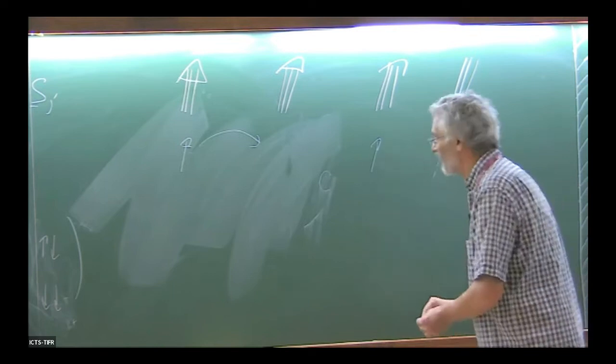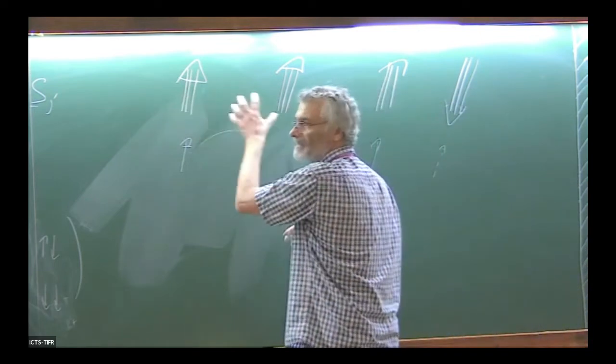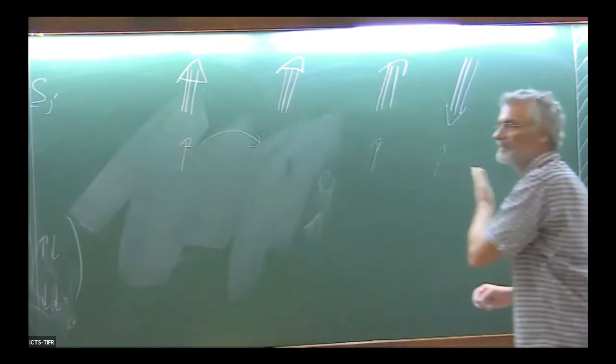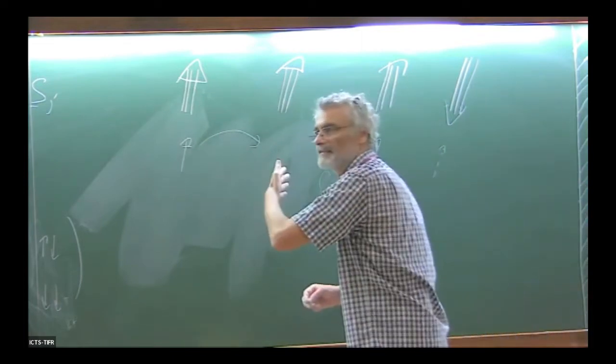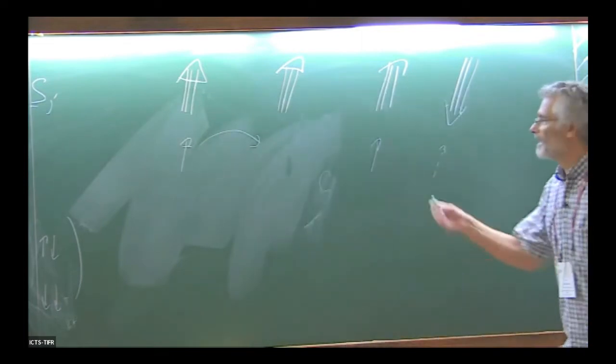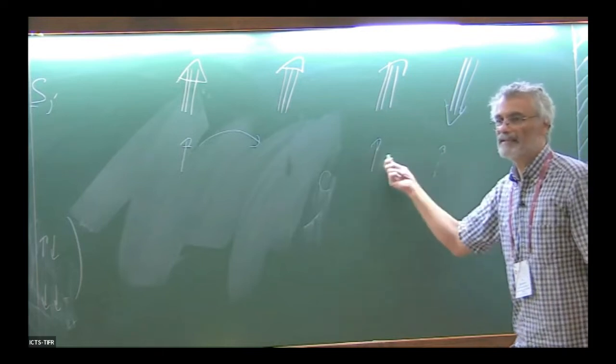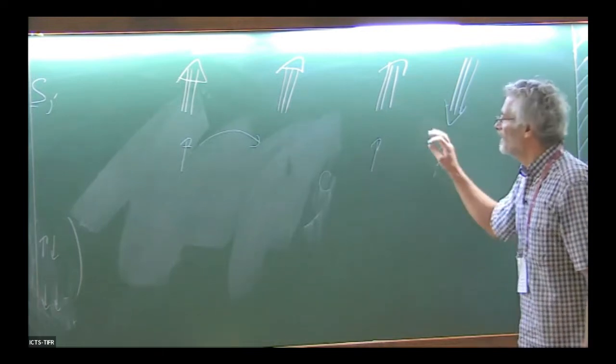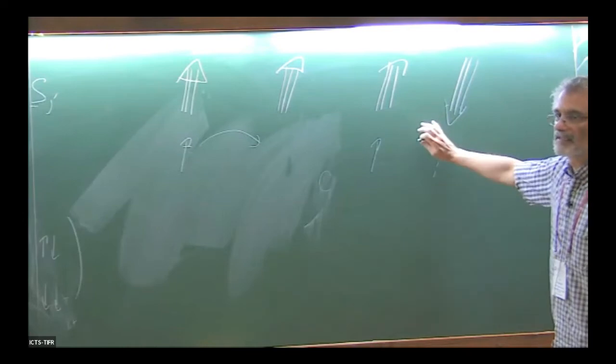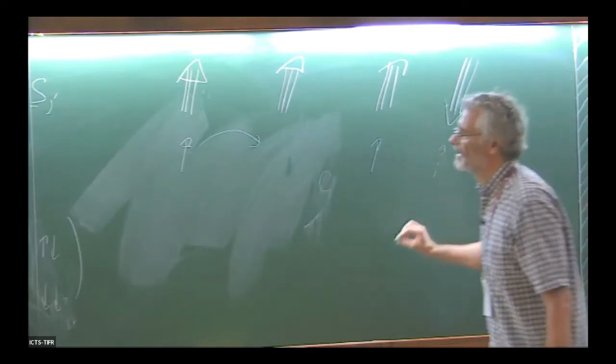So it means that if all the spins are parallel, then the electrons can freely move in the system. If it is an antiferromagnet, then they become localized. They cannot hop. And in this case, the resistivity is much higher. Okay.